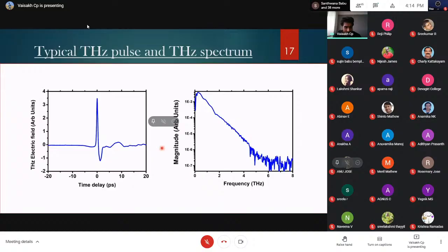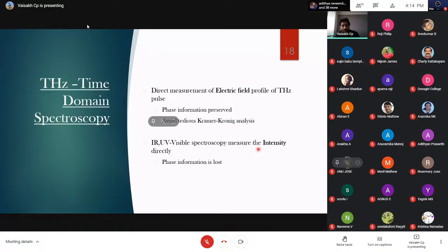We can see that this particular pulse is made of so many frequency components adding in, each with its own amplitude. And I have not shown the phase information, but it is there. The good thing about directly measuring the electric field is that phase information is preserved. We don't have to go through tedious Kramers-Kronig analysis to find out the material parameters, which is not the case usually with other spectroscopic techniques.